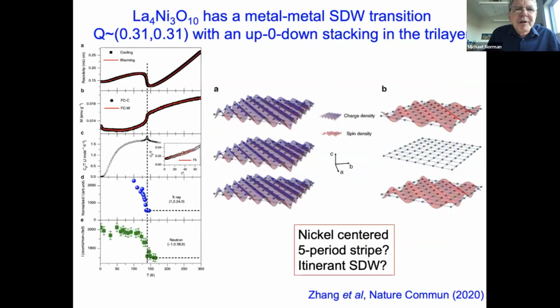Let me remind you, lanthanum 4310, a lot is known about it. This is work that we've done with John's group over the last number of years. The Q vector is 0.31, so slightly incommensurate. So it's close to being a 5-period stripe, but not quite. You have up zero down stacking within the trilayer. This is very unusual, right? Normally you would think about having up down up stacking, which is what you see in the reduced 438 material. But here you see up zero down stacking, which is a very, very unusual magnetic state within the trilayer. We've looked for harmonics in the data. We don't see them. So it looks like a sinusoidal spin density wave, classic chromium-like. But again, the wave vector is close to being commensurate, so you cannot completely rule out a 5-period stripe.